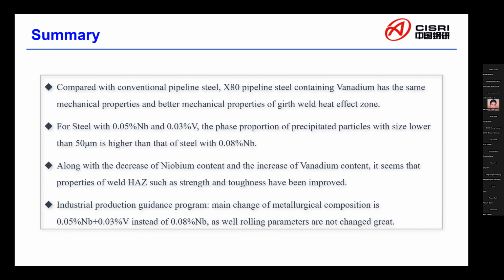The industrial production guidance program is that the main change of metallurgical composition is 0.05% niobium plus 0.03% vanadium instead of 0.08% niobium. As well, rolling parameters are not changed greatly.